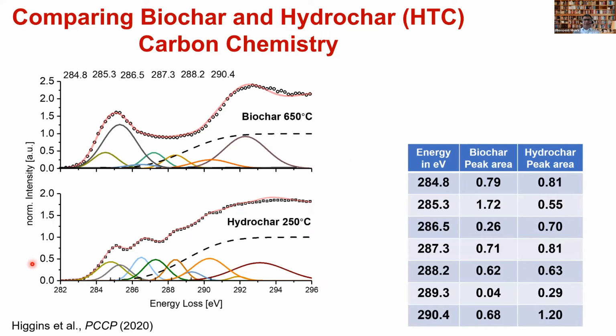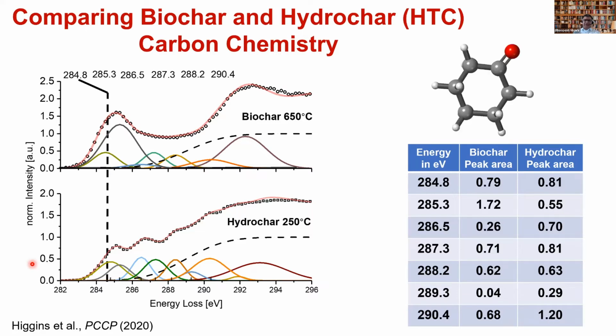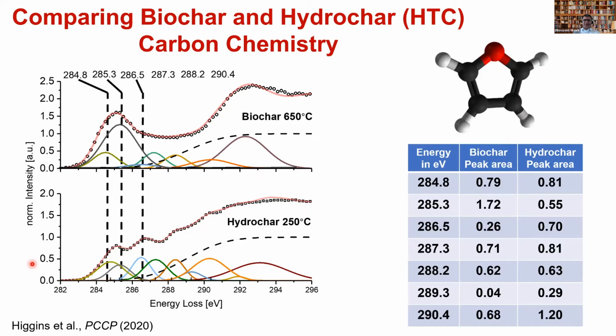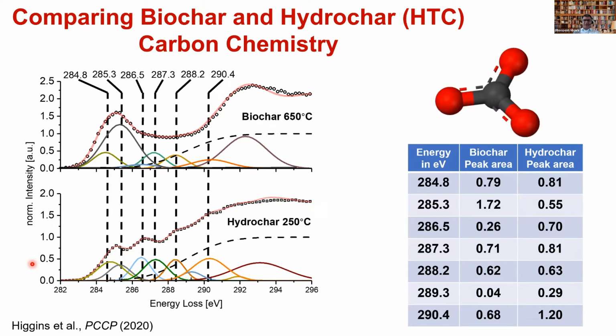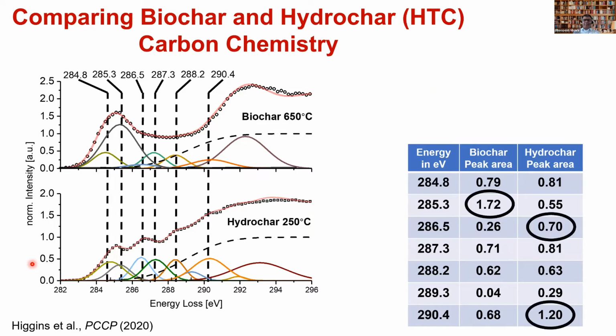So, but meanwhile, let me show you that when we used this X-ray Raman scattering to try to understand the difference between these two kinds of materials, biochar versus hydrochar, of course, we saw tremendous differences, because the way they're made is very different. So you have different kinds of transitions that we analyzed. And in a nutshell, I can tell you that you have a very high aromatic component for the biochar, and hydrochar is very different, which has much more carboxyl, carbonyl kind of component in it.